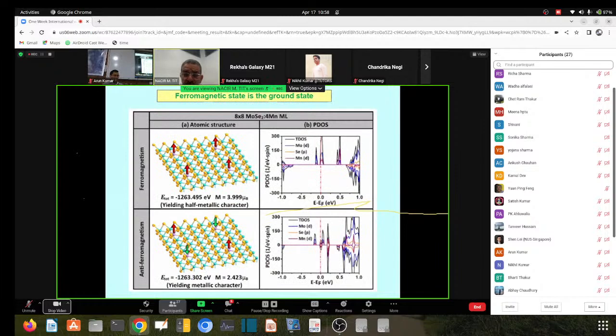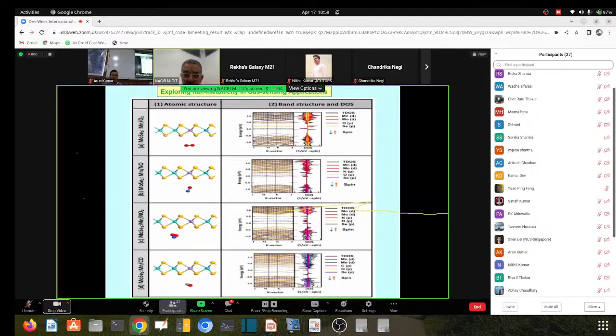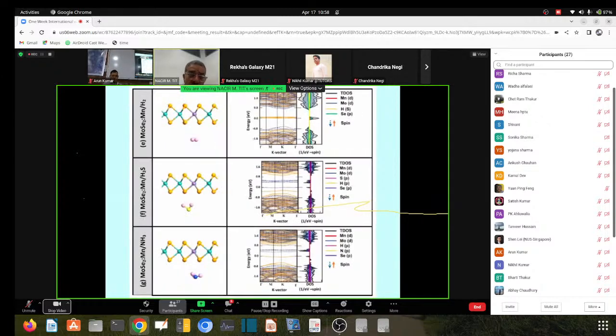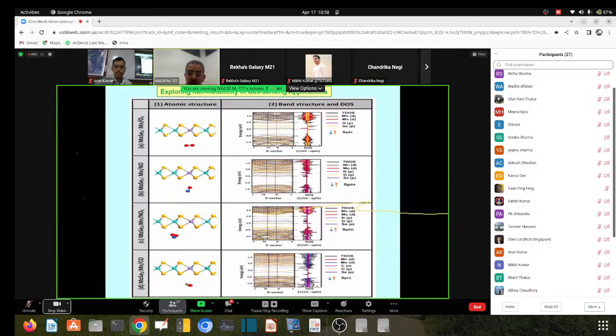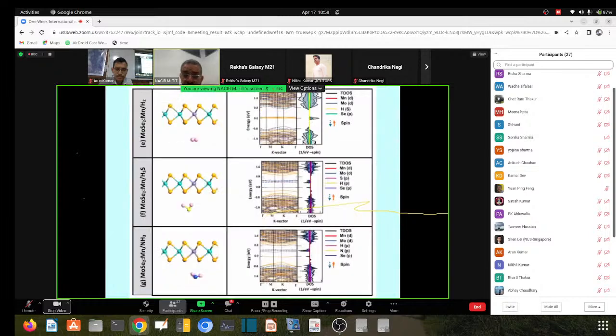Now thereafter we explored the half metallicity in gas sensing. So we did the absorption. We tested the absorption of oxygen, NO, NO2, CO, H2, H2S, and NH3. And we tested the atomic relaxation. We observed all of them are physisorptions, as you can see in the atomic structures. We tested the bands and density of states, and we saw that there is only one case, which is hydrogen, where the band structure remains basically robust, half metallic. Half metallic, as you can see here, spin up is conducting and spin down is semiconducting.